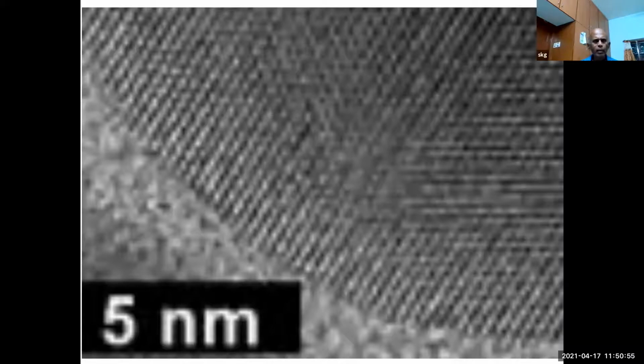This is a TEM picture. This is supposed to be a boundary of a silver nanoparticle with gold. What you see is beautiful layers characteristic of an FCC lattice, ABC, ABC. And occasionally you find stacking faults. And occasionally you see clusters. And you see lots of inhomogeneity.